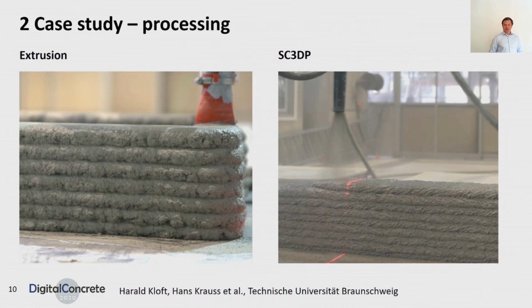Now here you see some pictures. On the right hand, you see that we indeed succeeded in spraying rectangular strands, which is not really an easy task. And that's why we need a very special material with very special rheology. And we use the same material for extrusion.